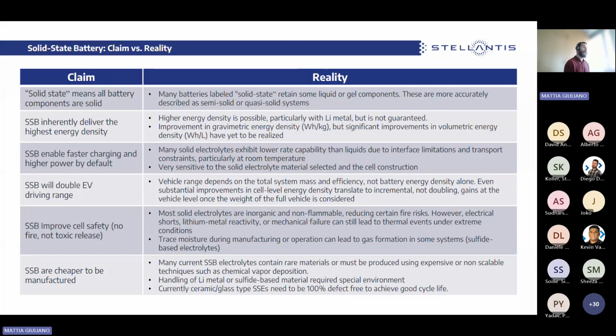Furthermore, traces of moisture, during manufacturing but also during operation, can lead to gas formation or reaction in some systems, in particular in sulfide-based electrolytes and in the presence of metallic lithium. In terms of manufacturing, many of the current solid-state battery electrolyte technologies contain rare materials and must be produced using expensive and not scalable techniques. So the manufacturing is still not very cost effective. Also consider the handling of very delicate materials like lithium metal or sulfide-based ones, which require a special environment. And for the ceramic solid-state electrolyte, it needs to be a 100% defect-free product in order to achieve interesting performance.